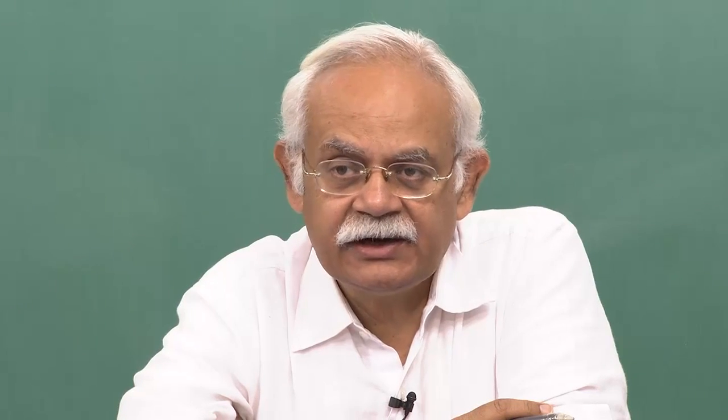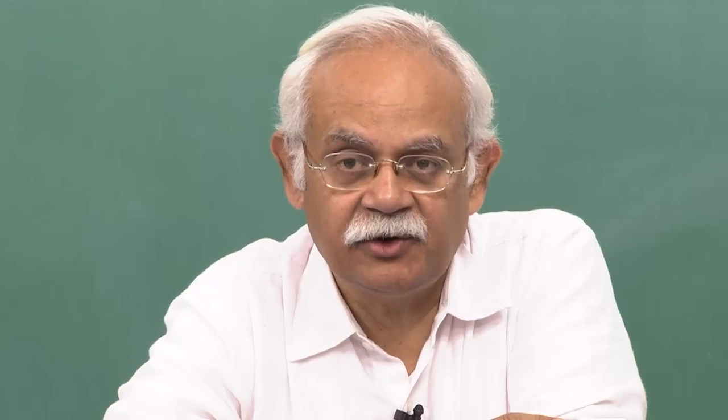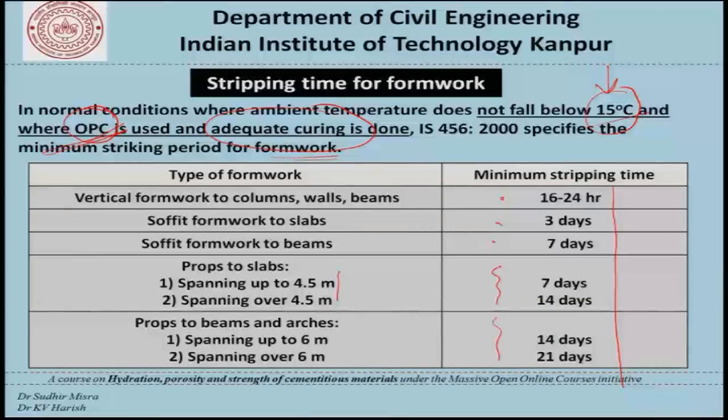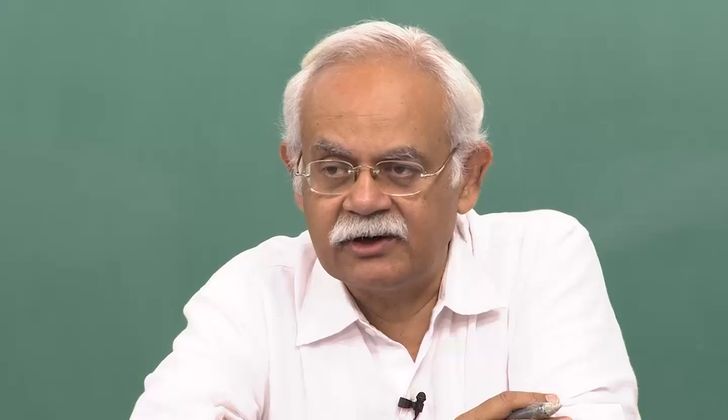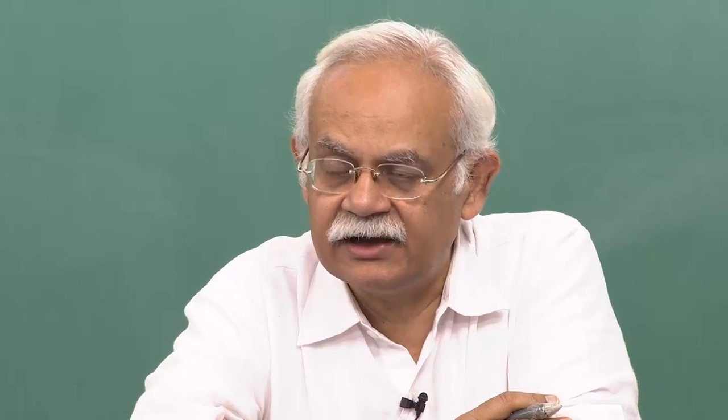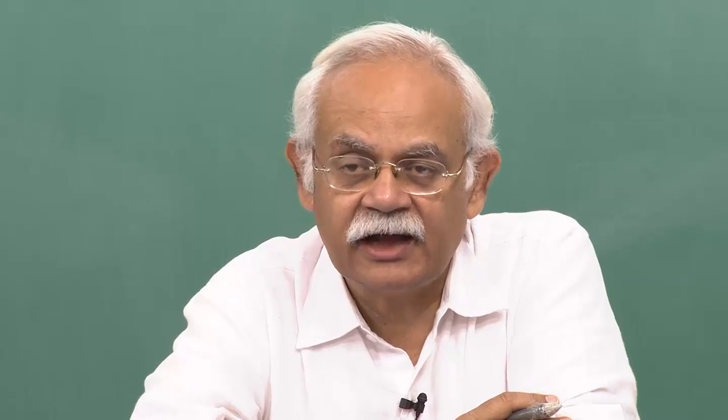This discussion of OPC versus non-OPC, that is cements where pozzolanic material has been used, is also very relevant from the point of view of appreciating the importance of curing and treating these timings here with a pinch of salt. We know that cement reacts with water to give us hydration products and calcium hydroxide, and it is this calcium hydroxide which reacts with the pozzolanic material to give us calcium silicate hydrates. So, it is believed in literature that hydration in PPC cements or pozzolanic Portland cements is slightly slower. That is, we have a slightly slower strength gain, even though the final strength may be higher depending again on the type of curing that we have done.